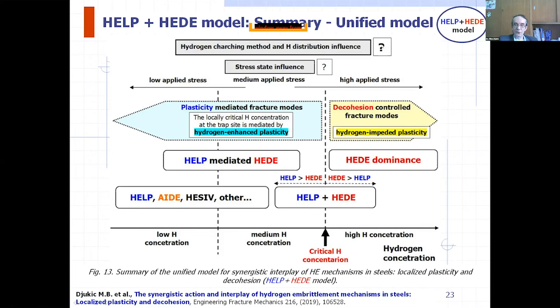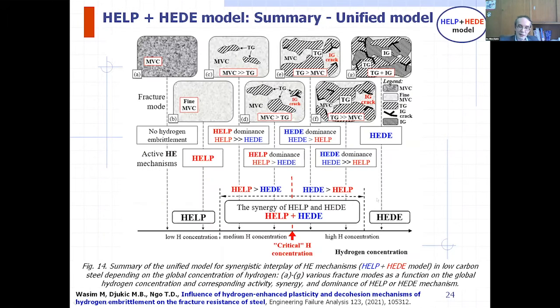Also, it is important to carefully examine the hydrogen charging method and hydrogen distribution influence on this transition from HELP to HEDE, and also stress influence, which indicates that high applied stress favors the initiation of the HEDE mechanism. More recently, in 2021, we proposed this summary for the HELP plus HEDE model in low carbon steel, where we pointed out that even in the case of HELP dominance at lower than the critical hydrogen concentration, we have local incidence due to activation of the HEDE mechanism, which didn't yet provide a sharp decline in mechanical properties, as you can see on the previous slides.